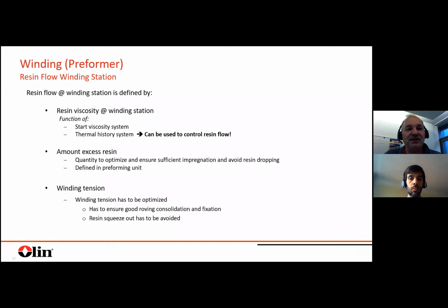The resin flow, for sure, is also defined by the amount of excess resin. So if you have more resin on your preform and you have a kind of force on it, it's squeezed out, especially if the viscosity is too low. And the winding tension itself has to be optimized to ensure a good consolidation of your part. But on the other hand, don't squeeze out the resin and deform the directed fibers.